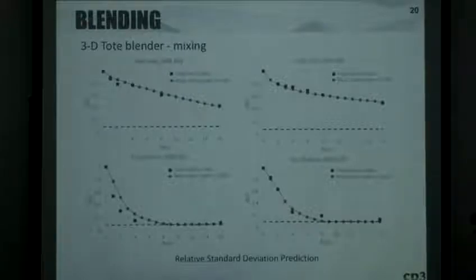So the top two plots are side-to-side. This is 40% fill, 60% fill. The black dots are the experimental measurements coming from the Rutgers paper. The red dots are from our multi-scale model. And again, we didn't backfit this to their data. This was all independently measured stuff. The bottom is top-to-bottom filling. Again, 40% fill, 60% fill. It works pretty well. There's a little discrepancy here.